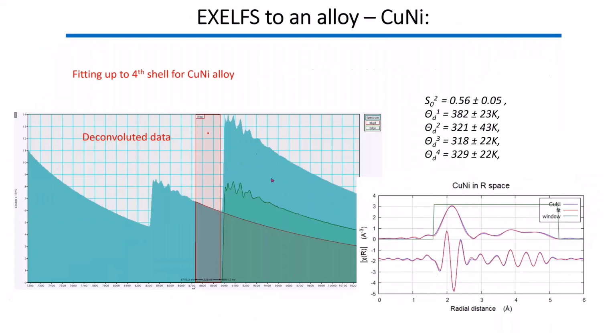And we can also apply this to an alloy as well, which is a copper nickel alloy. We can also fit up to 4 shells, and you can see that the Debye temperature fitted from here sits between copper and nickel for the alloy, which is very much consistent with what we found.